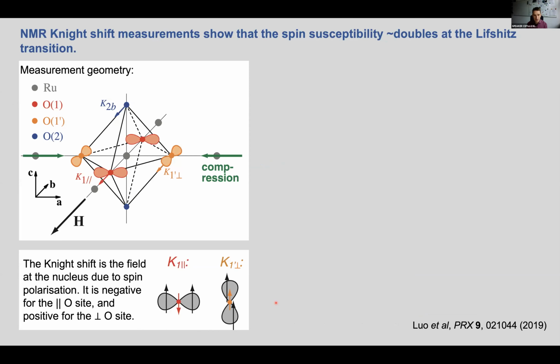My colleague Stuart Brown at UCLA has done NMR work on strontium ruthenate. So this is the essential measurement geometry. He's applying field in this direction, and that gives 3 inequivalent oxygen sites. We have this one which sits between these ruthenium sites, and that direction is aligned with the field direction. And we have this oxygen site that sits between these rutheniums, and that axis is perpendicular to the field direction.